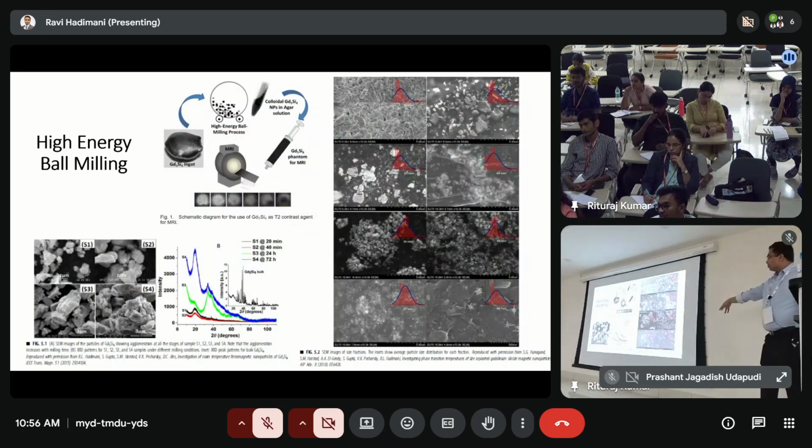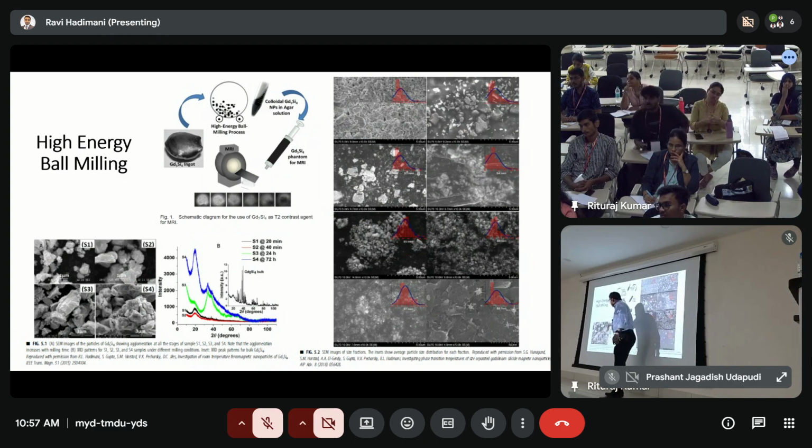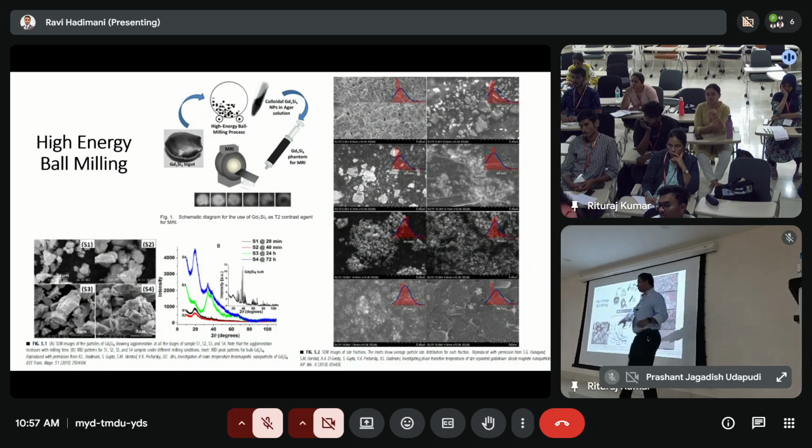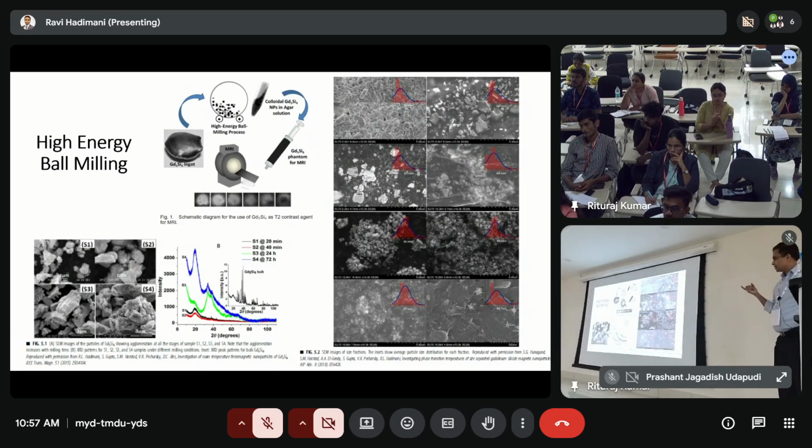And this is our ball milled nanoparticles, and you can get different sizes. We looked at it, and when we ball mill for more than an hour, it's completely amorphous, the black and red. So we had to use some media in between to absorb some energy back and retain crystallinity.